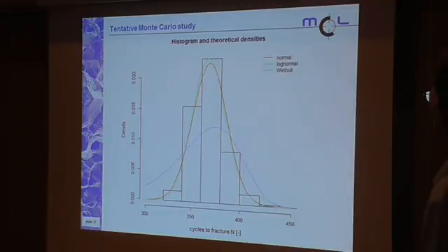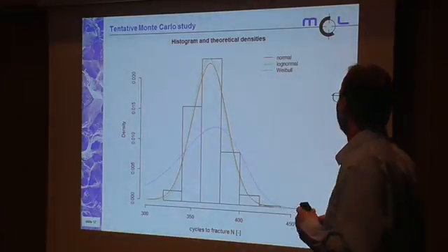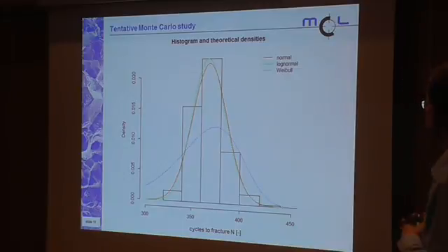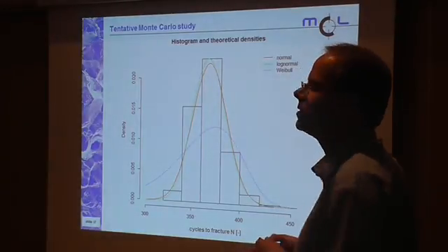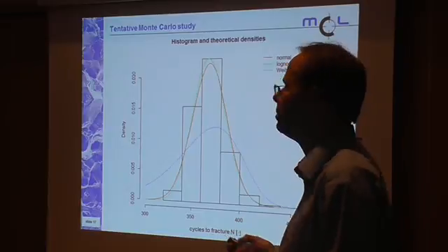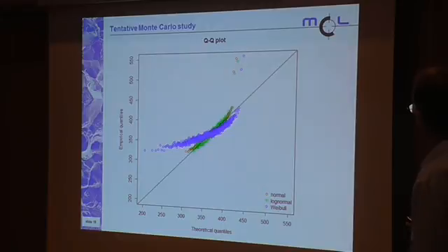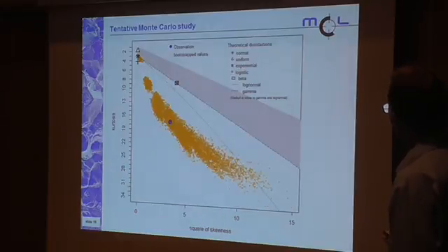And what we get is this empirical distribution, and of course we see that it is not a normal distribution due to its skewness. On the other hand, it's not a log normal and for sure not a Weibull distribution either. The question is, which kind of distribution could it be? Well, here again you see that the distributions are quite far off.